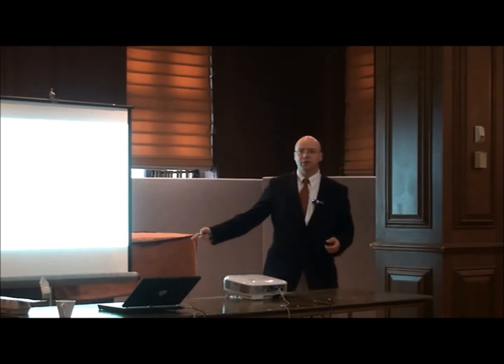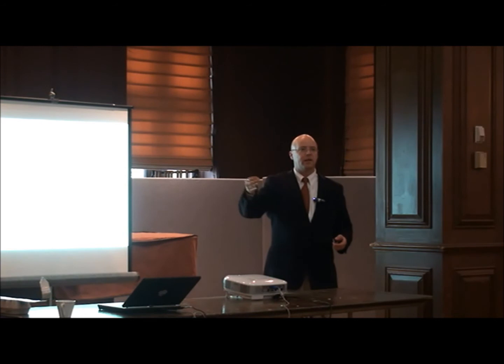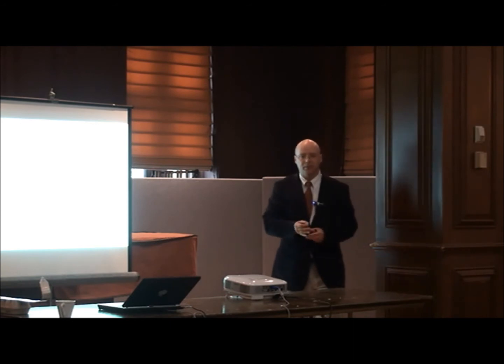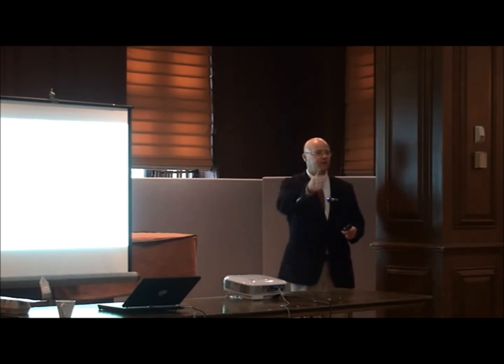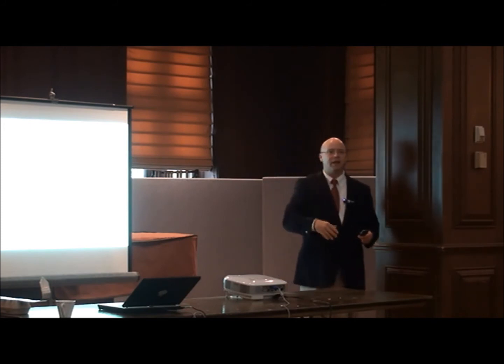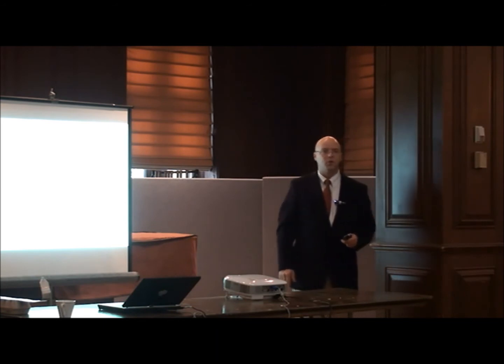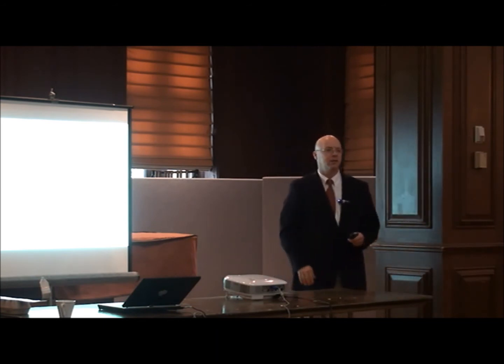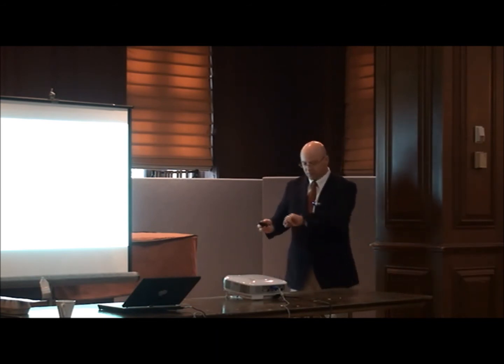And if you're doing that analysis at smaller than 10 times the spacing of the points that you measured, you're going to end up with strong directionality at 90 degrees, at 45 degrees, at 0 degrees when you run this analysis. So it's going to flaw your data at the finer scales. So that's something to watch out for.